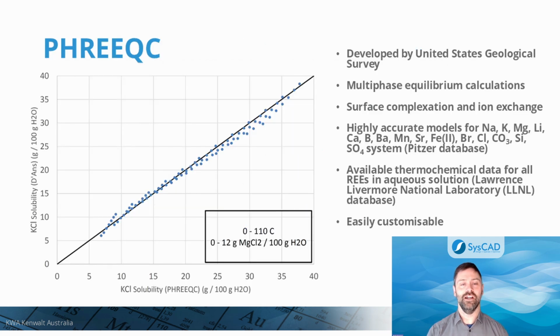In this presentation, we selected the thermodynamic calculation engine PHREEQC. This package, developed by the United States Geological Survey, is a freely available thermodynamic engine with an open-source database structure. 2 databases, the Pitzer.dat database and the LLNL.dat database, which were developed by Appelo et al. and the Lawrence Livermore National Laboratory, respectively, contained the required data for modeling rare earth chloride brines in hydrochloric acid solution.